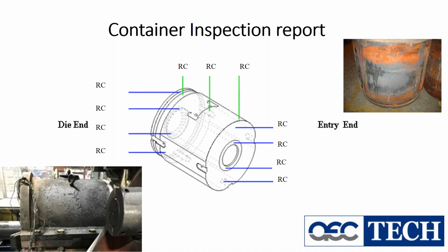We get a regular grinder. We grind them all off a few thou, making sure we take away any of the oxides, but we don't do it too much where we're going to work harden the surface. So it does take a little bit of touch, but work with your suppliers, monitor that stuff, keep track of it, and track the life of your containers. Don't just get a simple, yeah, it's good. You're going to know as the life of this container starts to move. If we supply a container at, say, 32 to 34 Rockwell, and it's 34 Rockwell on average, and we see the container start to look like this, it doesn't go from 34 to this in a day. What'll end up happening is you'll see 34, 28, 34, then 33, 24.